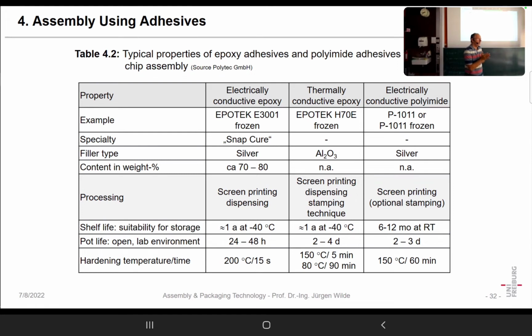Then we have the so-called pot life. That is the time how long the material can be at room temperature in the fabrication environment, or even on the screen. So maybe here they say 24 hours to 48 hours. That is quite a long time, but the main reason for that is it is a material which doesn't precisely have that reaction rate dependency on temperature.